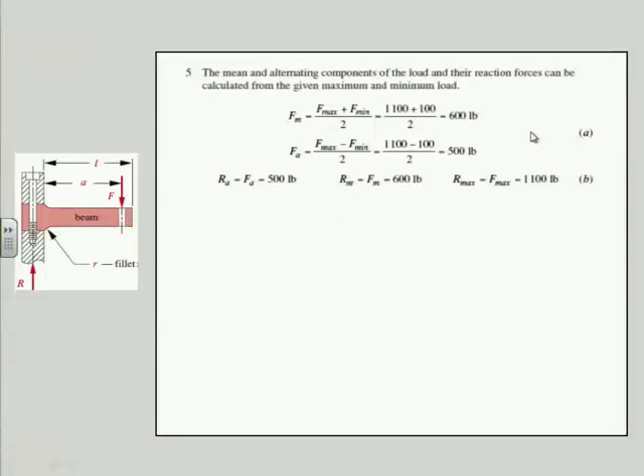So I start off by finding out what my components are for the mean and the alternating. So in essence, what I'm going to end up doing with this case, a fluctuating case, is I'm going to have two almost identical stress analysis computations. Equations are typically going to be the same because the loads and cross sections are the same in both cases, and the loads are in the same direction in both cases. I just have a different value. So I've got a value of 600 for the mean and 500 for the alternating. So I set the same set of equations up for both, just change the numbers. I'm doing it in a spreadsheet or MathCAD, MATLAB, TK Solver, whatever. It's very simple to do.